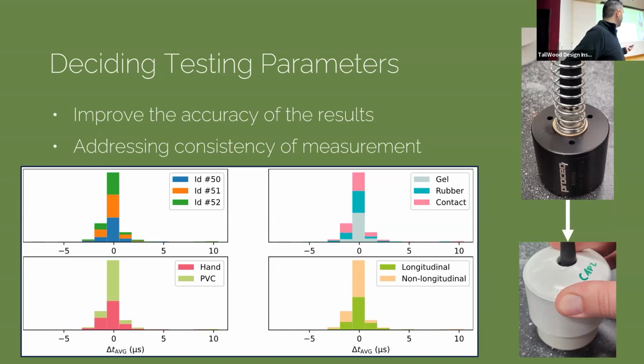It's very cheap but a very smart setup. It's based on a spring design, and there is a PVC case in which you press the sensor. Because of the spring inside the case, you apply consistent pressure every time, just to make sure that manual measurement is not going to cause a huge variation in the collected data.